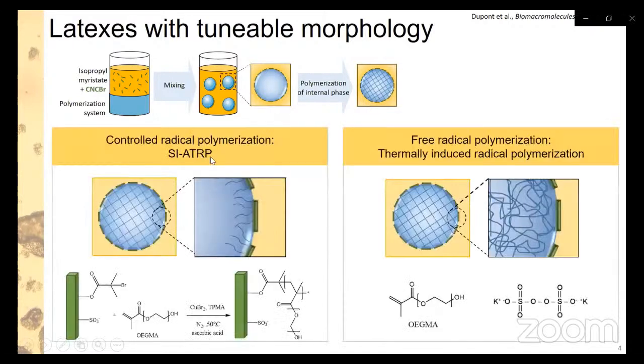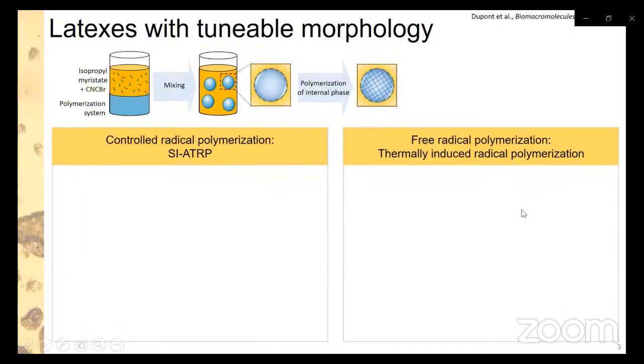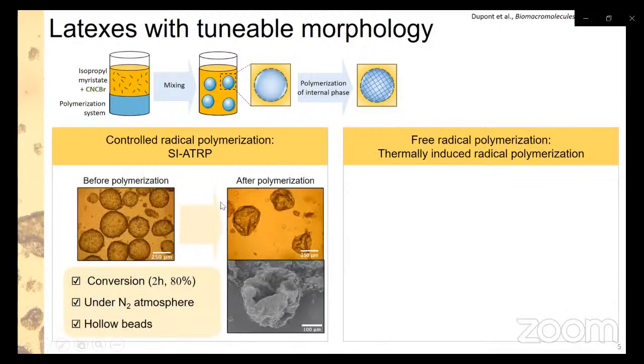We studied two types of radical polymerization. First, surface-initiated ATRP, taking advantage of the brominated functions on the surface of the CNC, and therefore on the surface of the droplet. We were able to grow this polymer from the surface of our object. On the other hand, free radical polymerization makes no link between the CNC and the polymer. For the first system, we obtained within 2 hours a very good conversion of the monomer, about 80%. And we obtained this hollow bead morphology, which shows that we effectively have grown the polymer from the surface of our emulsion, leaving an inner void inside the capsule.